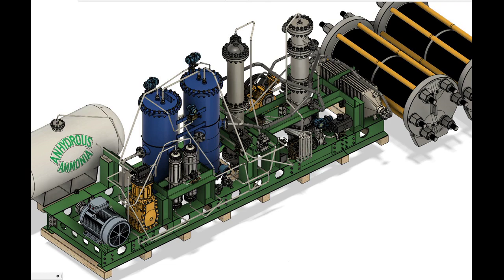The principal advantage of the ionic liquid design is the elimination of the failure-prone diaphragm disc, as well as its considerably higher volumetric flow capacity, even higher than traditional reciprocating compressors. This is due to two factors. Firstly, the elimination of the connecting rod, which allows on its own a much higher stroke-to-bore ratio. Secondly, this high stroke-to-bore ratio can be realized in a single compression stroke without excessive heat buildup, owing to the high heat capacity of the ionic liquid, which is able to absorb most if not all the heat generated.